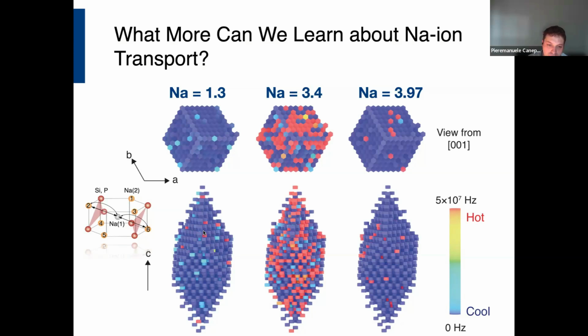So here I'm showing you some snapshots of the kinetic Monte Carlo at different compositions: sodium 1.3, sodium 3.4, sodium 3.97. Sodium 3.97 means high silicon content. And here you can see most of these cells, the prismatic cells, are violet because there is small sodium ion transport activity, and there are some isolated red, meaning that there is high frequency there. These are active cells, but because the red are diluted in the violet, there are effectively not a lot of percolation channels. When we go to the fastest ion conductor, sodium 3.4, you can see that all the red boxes or prismatic cells are connected to each other. There is a lot of activity, and of course this determines the path of percolation for sodium ions.